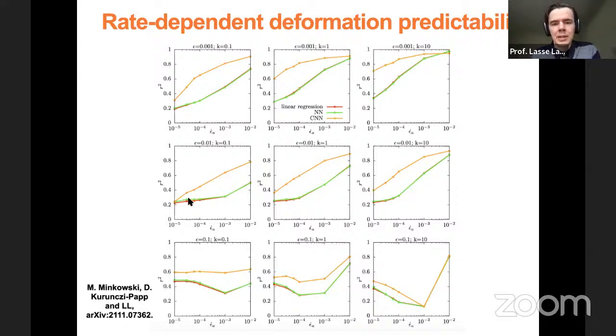This is also true for, let's say, this slightly larger strain. However, here for the even larger strain, and if your driving spring is stiff enough, you get a non-monotonic behavior. So initially it goes down as you increase the rate, but then there's a minimum, and then for the very large strain rate, you again improve the predictability.